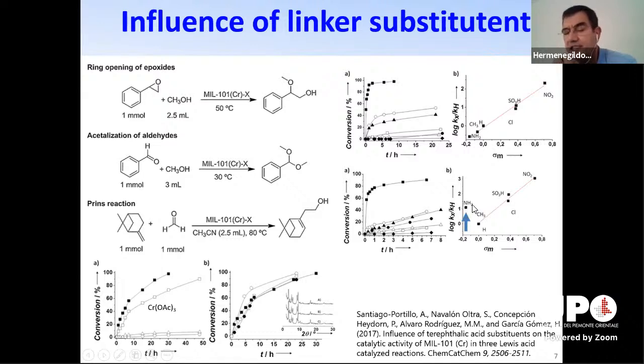And this is very interesting because many times it has been claimed that you need an acid-base pair in the same material, and if you have this type of acid and base pairs in the same solid, then you can run the reaction with much lower acid strength. And here we have an example. This example is the acetalization of aldehydes, in which we study the activity of MIL-101 chromium and vary the substituent on the terephthalate linker, and these are the results: there is a big increase in the initial reaction rate when we have different substituents. I have to mention here that this is a logarithm plot, so this increase is not small. This increase is about 50% of the initial rate, so here the ammonium is playing an important role.